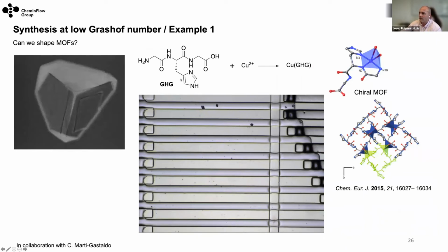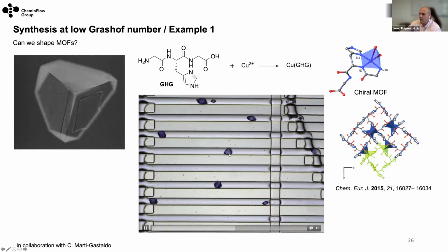So we have this peptide that, when it reacts with copper, forms this chiral MOF. This was done in collaboration with Carlos Martí Gastaldo at the University of Valencia. So what we have is, again, our double layer microfluidic device, and what you can see here is how this MOF crystal grows in these confined environments.